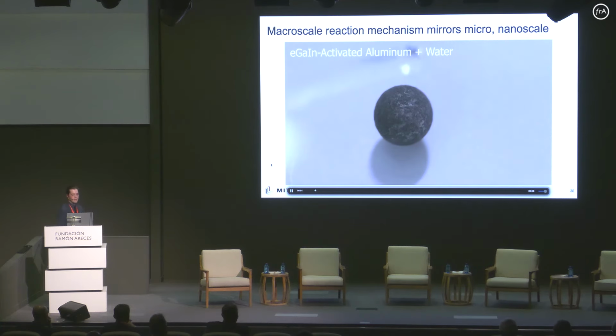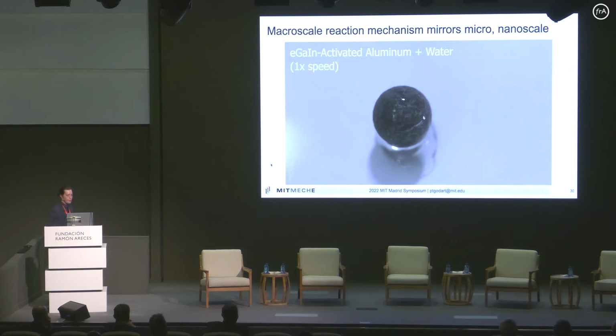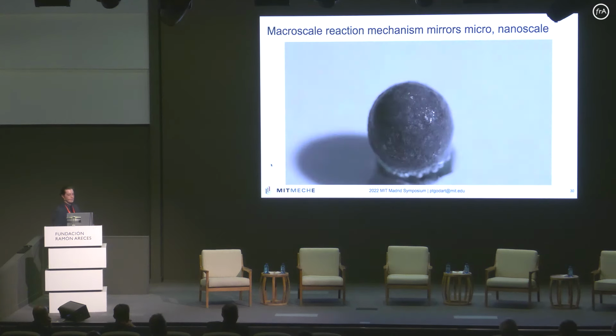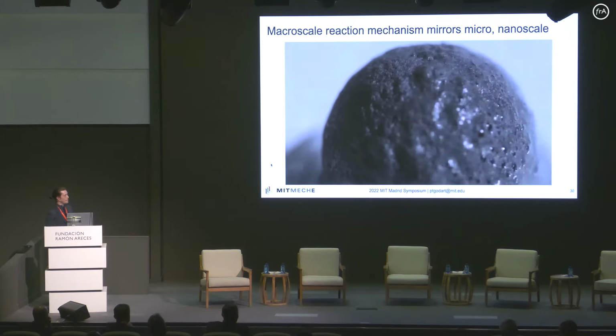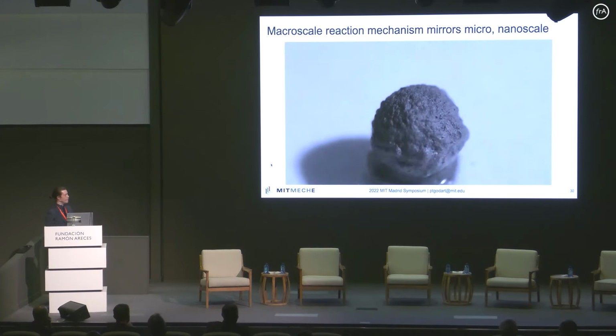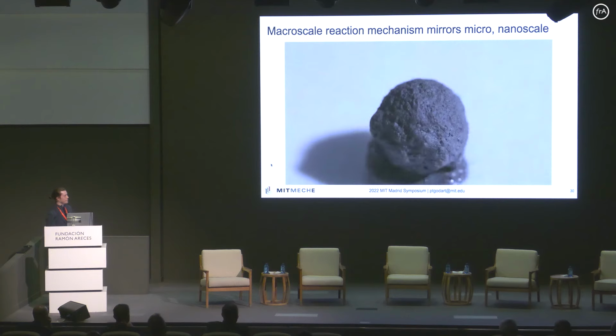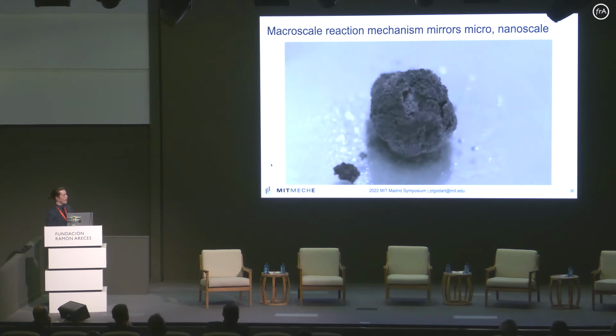So here is a 6 millimeter aluminum ball bearing, very pure aluminum ball bearing, that's been treated with the gallium and indium. I apply a drop of water onto it. This is in real time. You can see immediately hydrogen is being generated. And because of the heat, we have all these interesting secondary thermal processes. You'll see this popcorning effect happen.